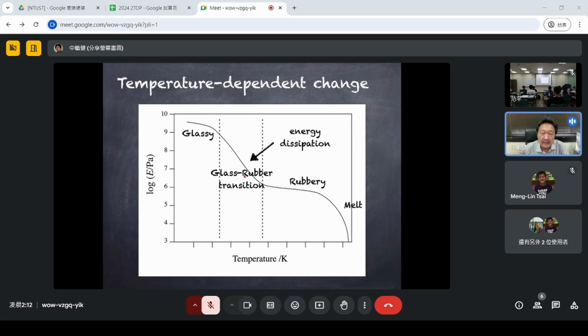More interestingly, if the material is in this situation, energy dissipation occurs. In the case of a bouncing ball, room temperature is around here, so it shows a rubbery state. But in the case of the non-bouncing ball, room temperature is around here. That's the reason why if you raise the temperature by putting it in hot water, it comes into this region, and when cooled down it goes to the glassy region. And here in this region, energy dissipation occurs. That's the reason why this non-bouncing ball doesn't bounce.